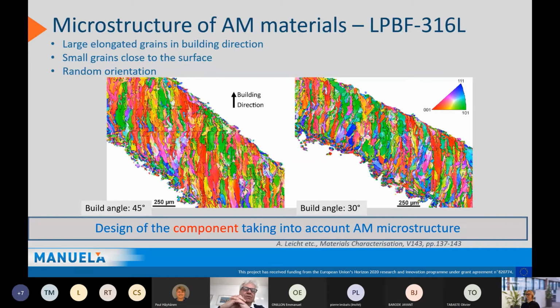However, if you go into details, I'm a little bit too materials oriented. You can have certain elongated grains in the building direction. These are so-called EBSD maps, but with a little bit smaller grains closer to the surface, and you see that there is a surface roughness, so there could be random orientation. So it's very important, if you go back to the work done by Manu and CSM, that when you go into designing a component, you really need to take into account the AM microstructure, that it is specific, it has its inherent characteristics. So this is something we have a lot of knowledge about inside Manuela.